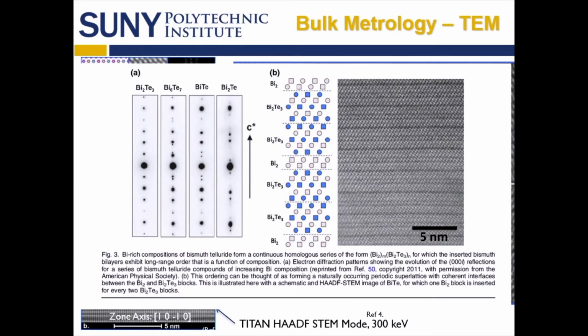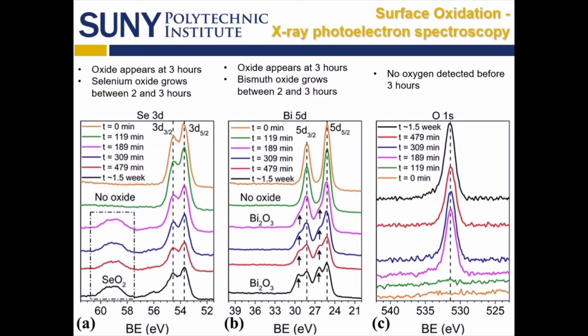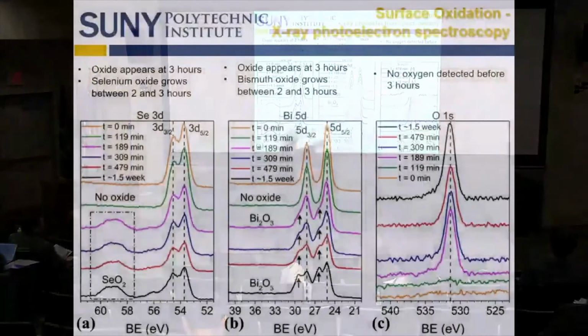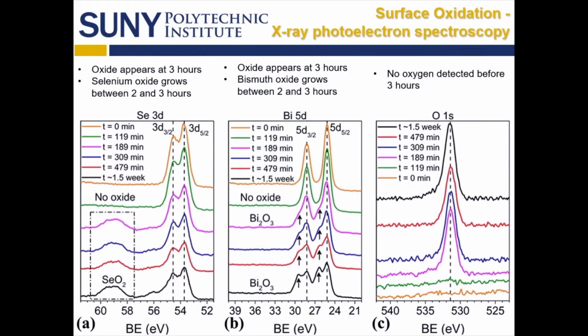These bismuth bilayers are important because they've been observed in X-ray diffraction and TEM studies. So we did a time-dependent oxidation study of the bismuth selenide, and if you just look at the oxygen 1s peak here, after 119 minutes, 2 hours, there's no oxygen peak. A little longer, there's an oxygen peak. You can see the change in the bismuth 5d and selenium 3d peaks with time. So we knew that there was oxidation going on.